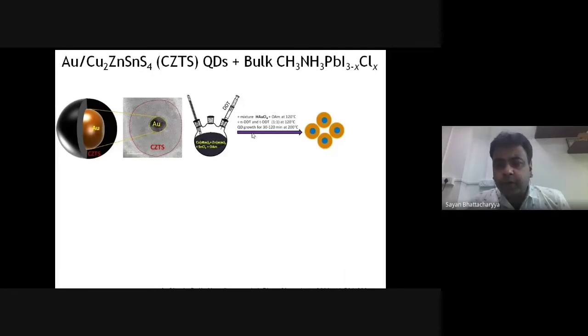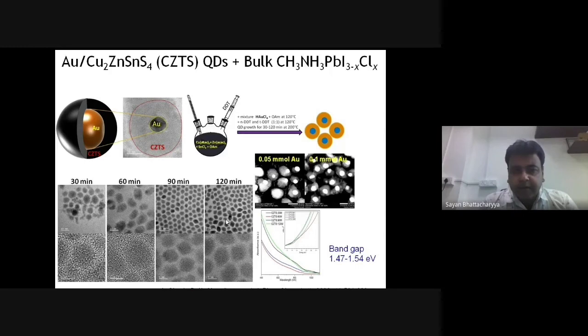Okay, the other thing that I'm going to show you here is another type of quantum dot, which is a core shell. This is gold at the core, and a CZTS quantum dot, you know, this is the shell. So you can vary the size of this by varying the reaction time from 30 to 120 minutes, means two hours. So you can vary the band gap this way, 1.47 to 1.54 electron volt.